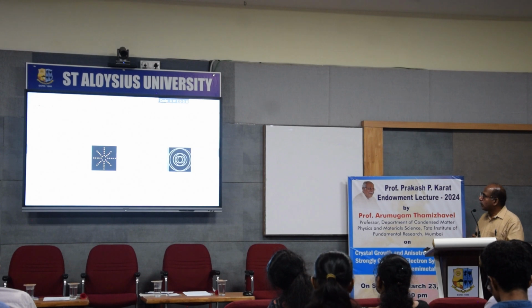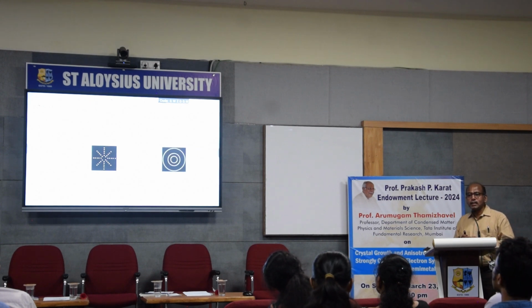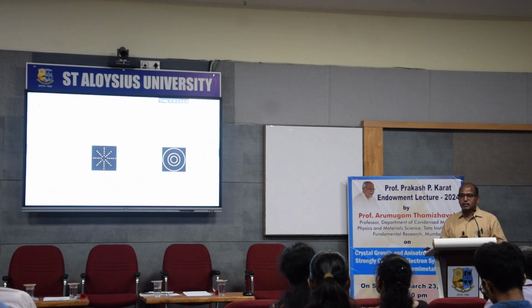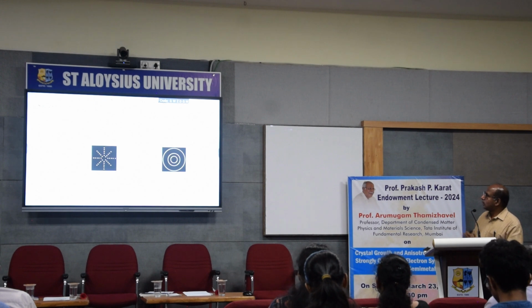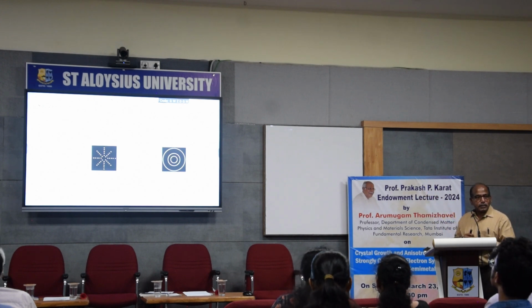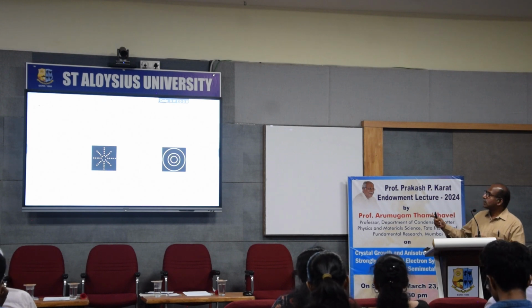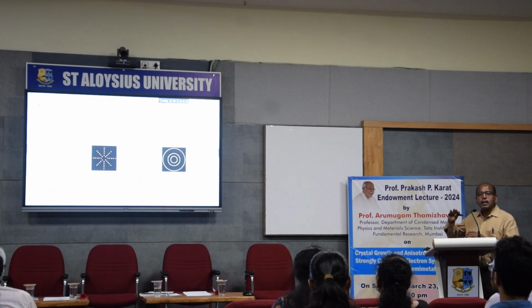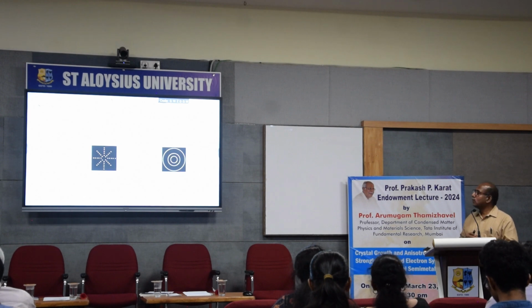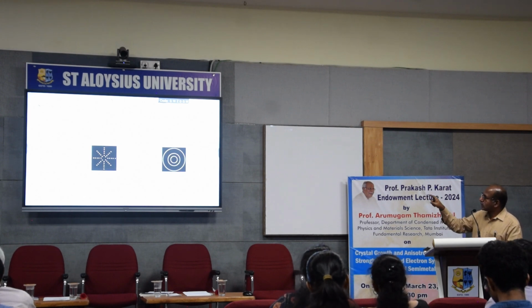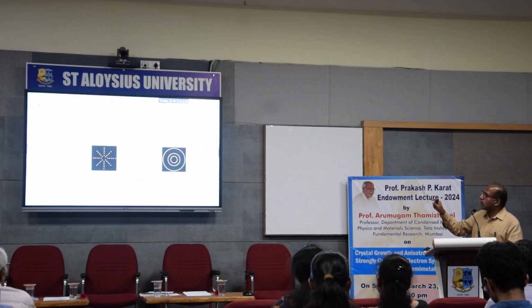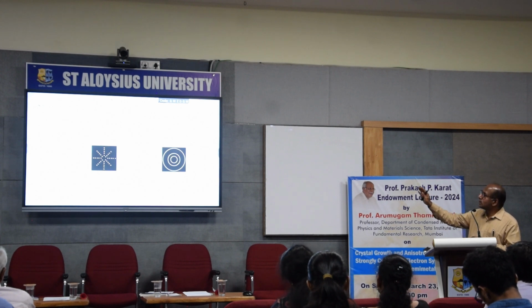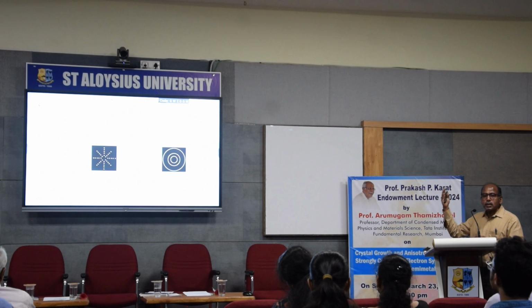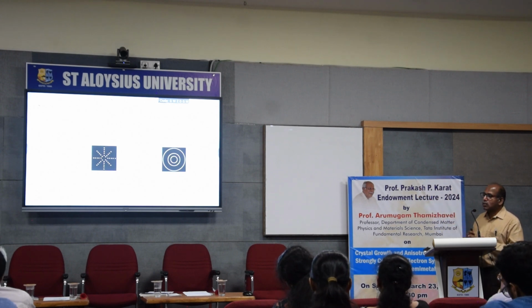On the other hand, a polycrystalline sample has a large number of tiny crystallites, and each grain is a single crystal. Now if you look at this right side figure, there are various grains which are oriented in different directions. Each grain will produce diffraction spots as shown on the left-hand side, but since they are oriented in different directions, the spots will be slightly tilted. If you put all of them together, you will see these kinds of concentric rings. If you look at the left-hand side figure and note very carefully at the center, you can see a circle. If you connect all the dots, you will see a circle. Similarly, since these grains, which are oriented in different directions, produce diffraction spots at different angles, they constitute this kind of concentric rings.